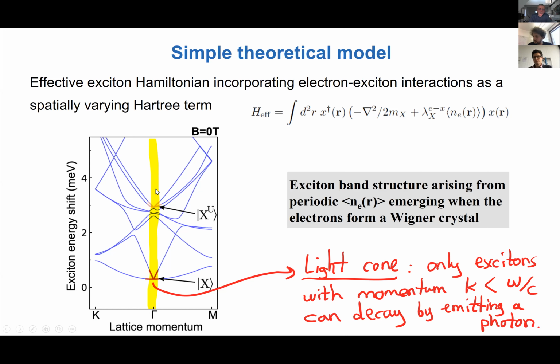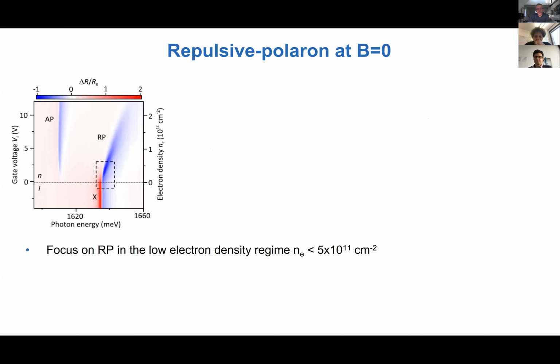And this yellow area is the light cone. So this is the region of momenta of excitons which can really decay by emitting a photon. And this is normally what we see. Again, actually, this dispersion exists only outside the light cone, but let's leave this aside. But the main point is that there's a new resonance that picks up an oscillator strength because of its mixing with the true K equals 0 excitons. So that's basically what we would expect to see.